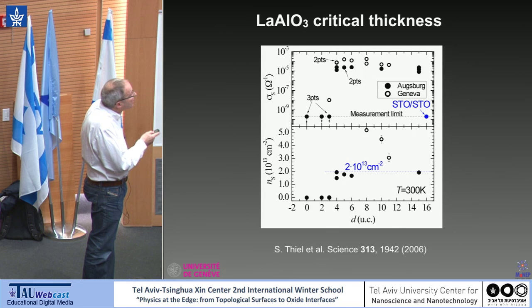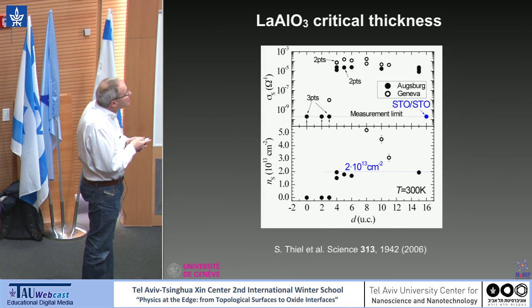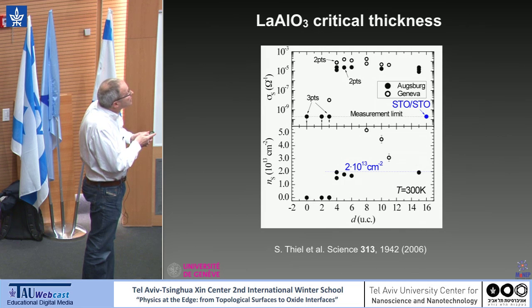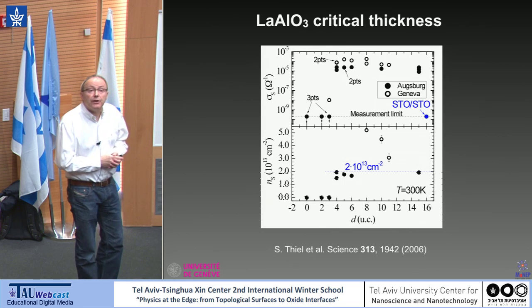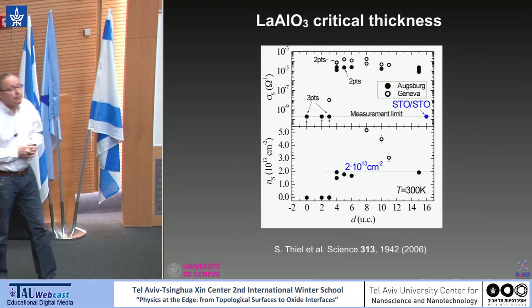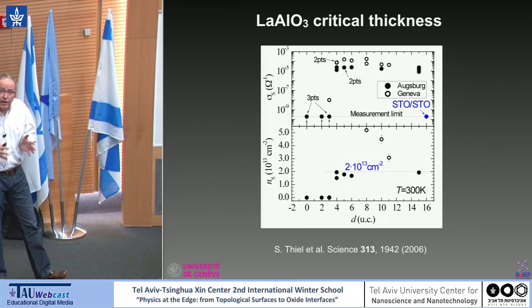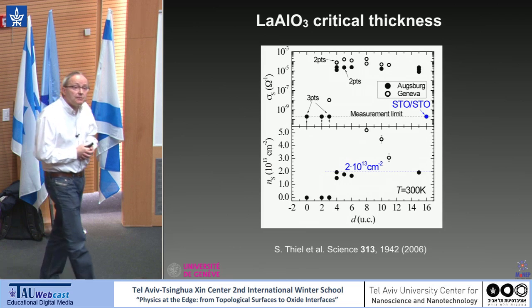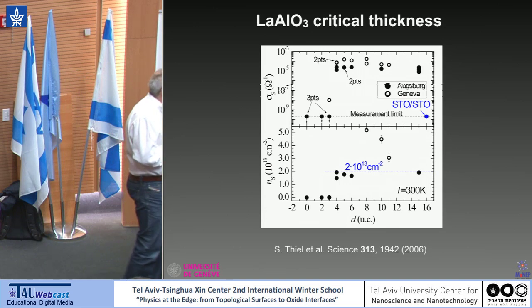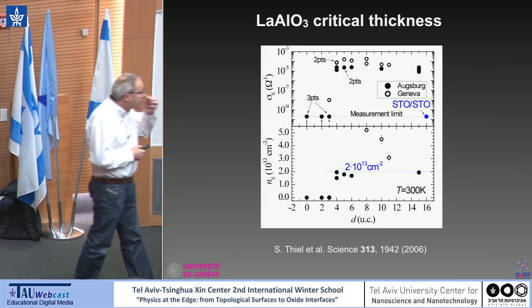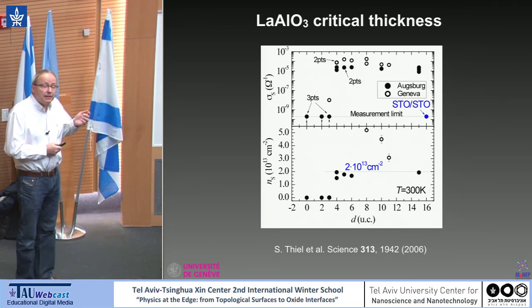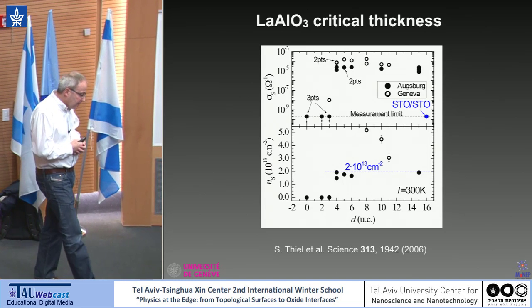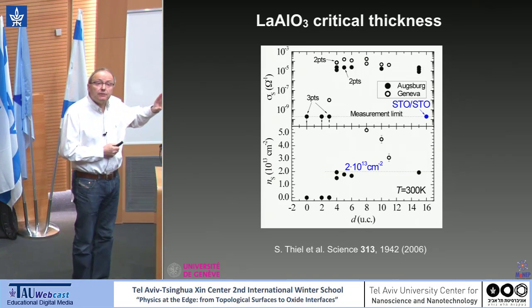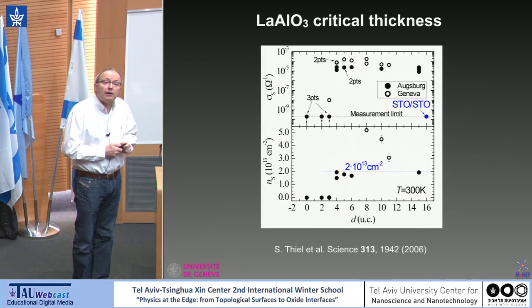Conductance versus lanthanum aluminate thickness in unit cells: 1, 2, 3, insulating; 4 unit cells, conducting. And you see all these points measured in Geneva. This is a very robust result, which has been observed in at least 5 or 6 groups. Now, a few years ago, with colleagues at PSI, we decided to further test this polar catastrophe scenario.